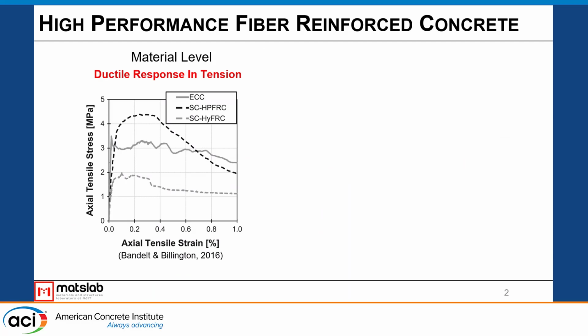So we first need to understand what HPFRCCs, or high-performance fiber-reinforced concretes, are. At a high level, these are cementitious and concrete materials that have been reinforced with steel or plastic fibers. When we do tests at the material level, what we'll typically see is a ductile response in tension. In contrast to typical concrete, where we'll ignore the tensile properties of the material, what we can see in the plot below of various HPFRCCs is that these materials offer substantial tensile strain capacity.